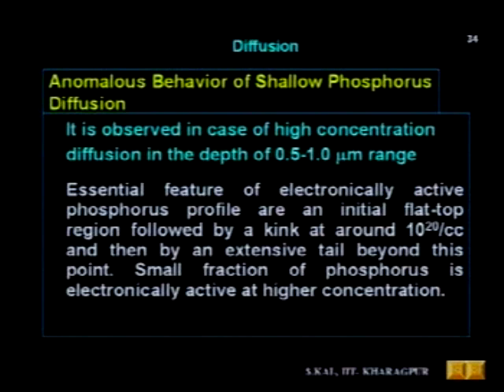In case of high concentration diffusion, in the depth of 0.5 to 1 micron range, an anomalous behavior of the doping profile of phosphorus has been observed. What is that? The active phosphorus profile looks like an initial flat top region followed by a kink at around 10 to the power 20 per cc, and then by an extensive tail beyond this point. A small fraction of phosphorus is electronically active at high concentration region.